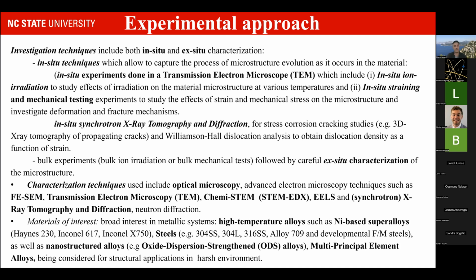Another technique that I have used very fondly, I would say, is in situ synchrotron X-ray tomography and diffraction for a couple of projects that I was part of in the past, such as stress corrosion cracking studies of canister steels, 304 and 316, or more particularly in situ synchrotron X-ray diffraction techniques to get information on dislocation densities as a function of strain through Williamson-Hall dislocation analysis.